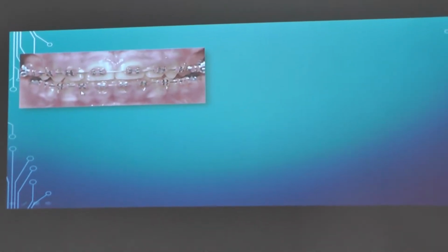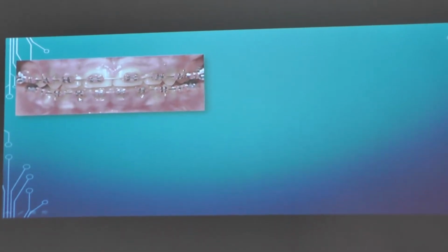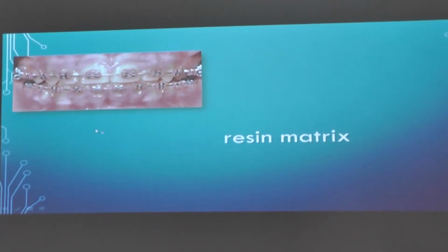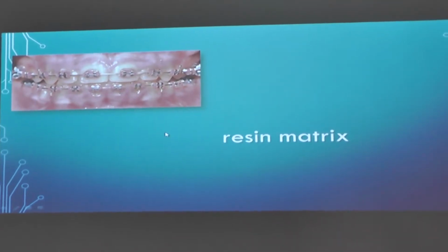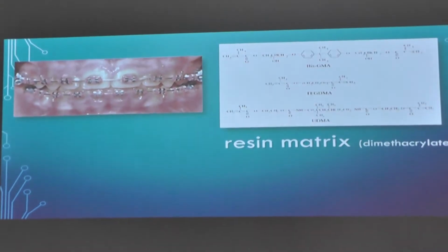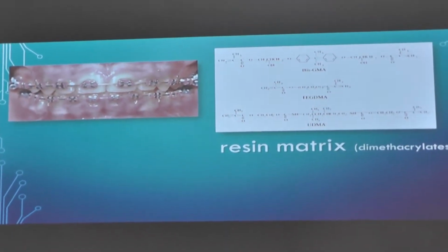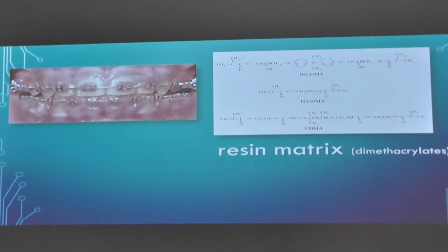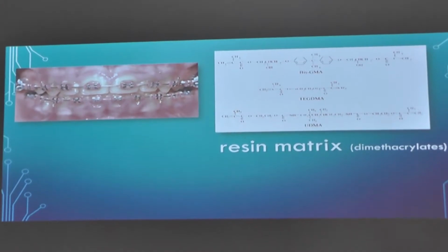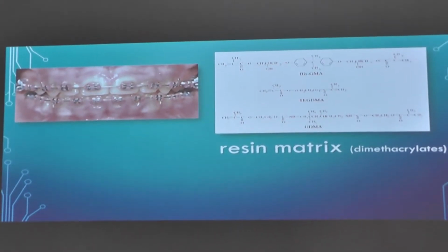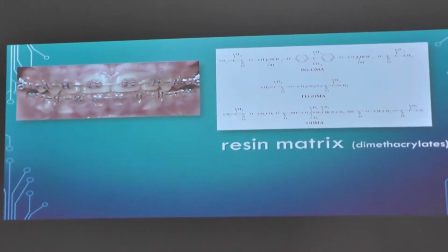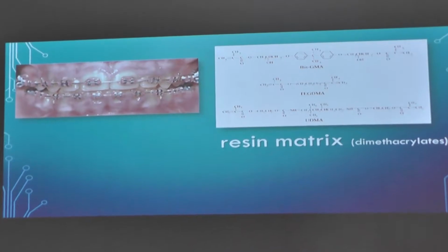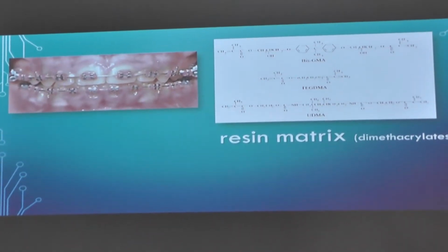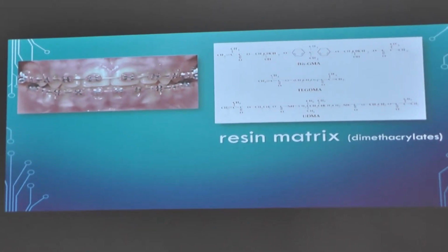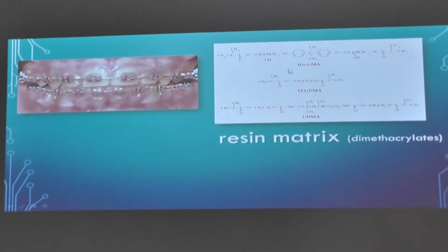So this is the modern adhesive, or modern adhesive technique, and an appliance that is bonded to the teeth. And what we need first is the resin matrix. And why? Because any adhesive first has to be liquid in order to wet the surfaces. This is valid for all adhesives, no matter the application or the industry or the profession. But in such a manner the adhesive withstands small shear movements. But when the shear movements are increased, or it should resist tensile forces, it has to be polymerized and solid. So this resin matrix is used because it can polymerize.